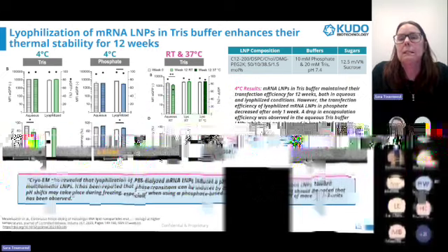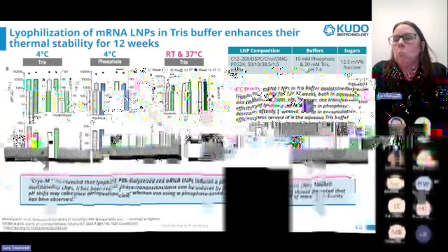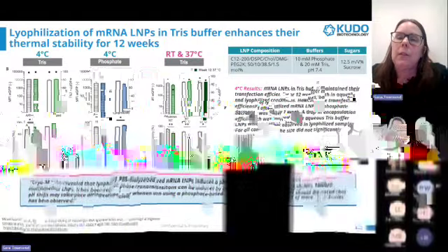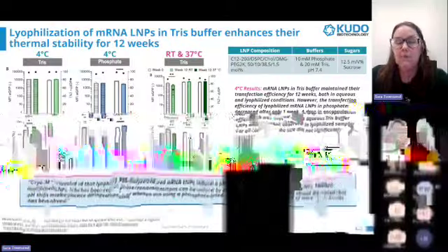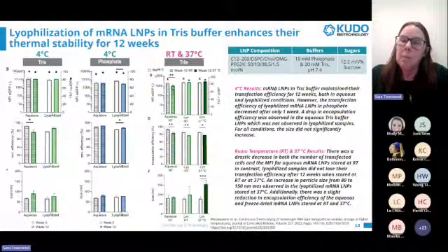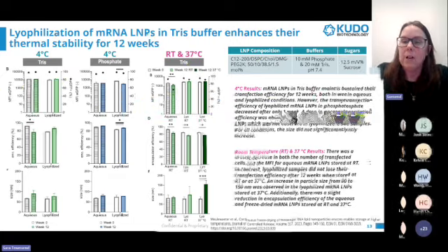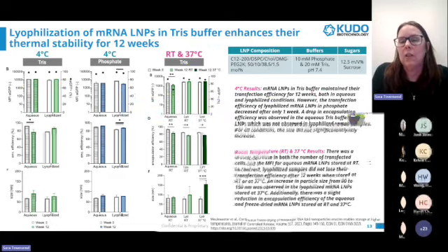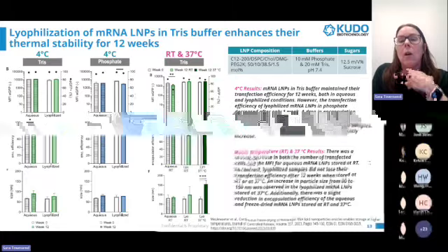For their 4C stability, Moderna used the 10 millimolar phosphate and tris at the 20-to-1 weight ratio. They also used the tris formulation for their study at room temperature and 37 degrees. At 4C, the lyophilized mRNA-LNPs in tris maintained both their encapsulation and transfection efficiencies for the 12 weeks, but PBS dropped after only 1 week. The tris formulation at room temperature behaved very well and did not show significant effect in transfection or encapsulation efficiency, or particle size.